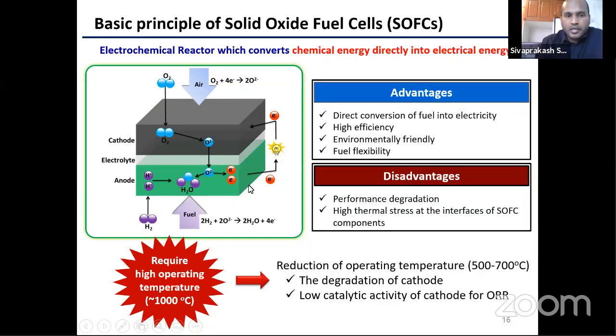The anode is mainly composed of nickel and zirconia composite materials. The electrolyte is mainly composed of stabilized zirconia ceramic membrane. The cathode is composed of perovskite materials like lanthanum strontium manganite, or lanthanum strontium cobalt.